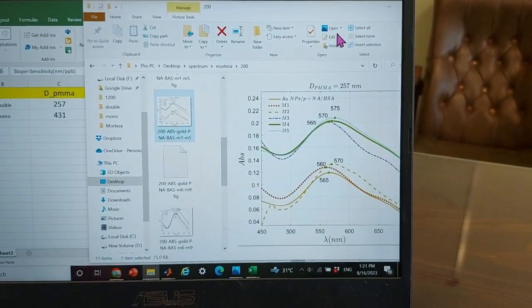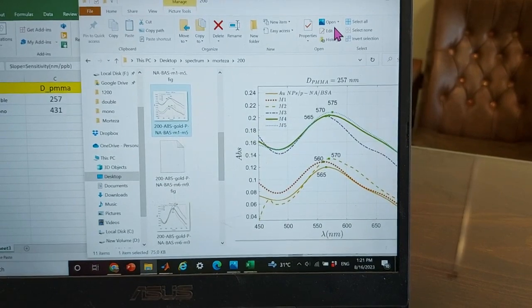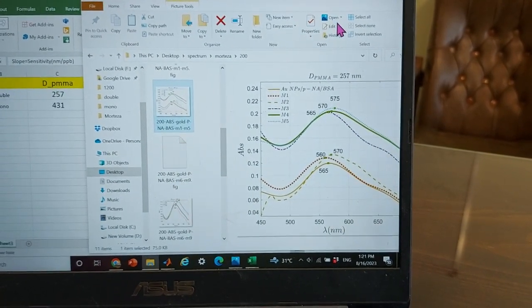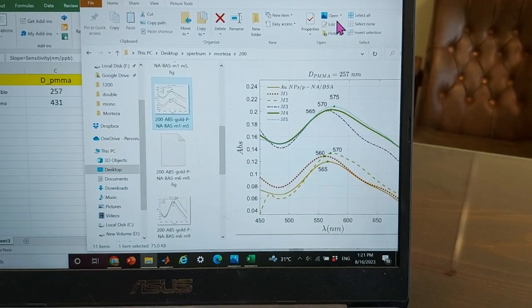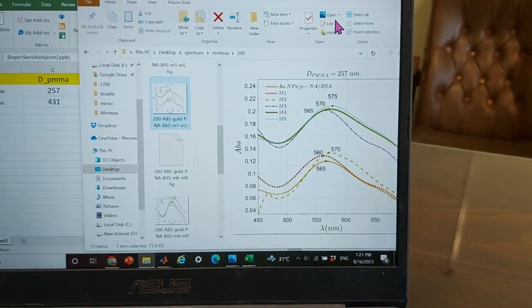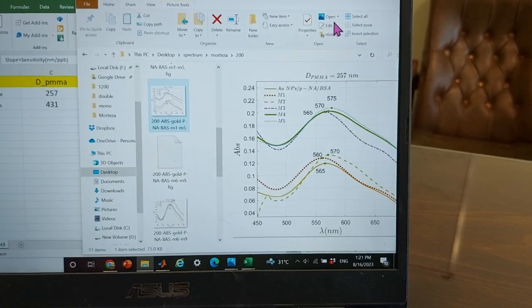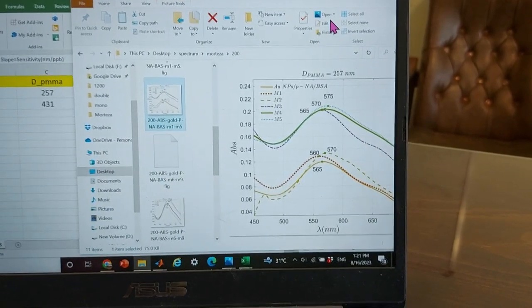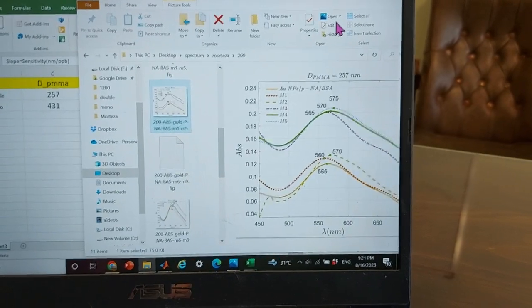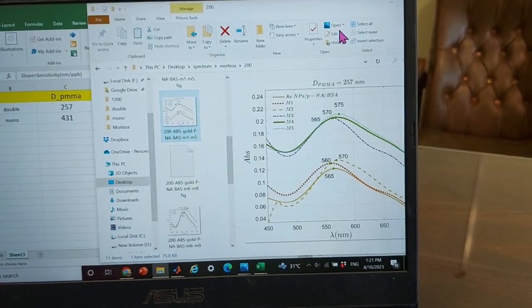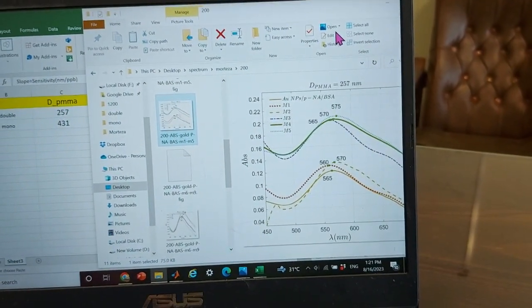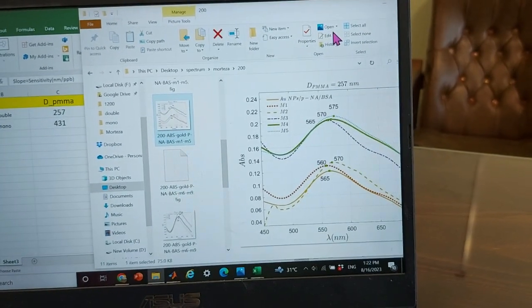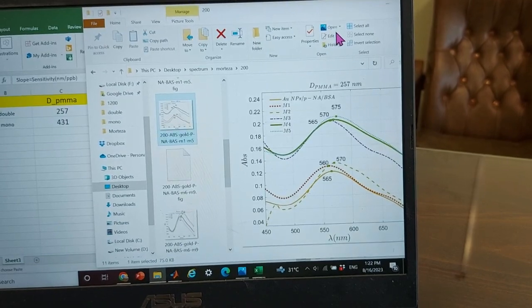Because we have big polymers, the electromagnetic field of each nanoparticle cannot interfere with the others in a good way, so the sensitivity is lower. In your case, fortunately, we have the same result: the less distance, the higher sensitivity. In the double layer, you have smaller nanoparticles, but they are far from each other.